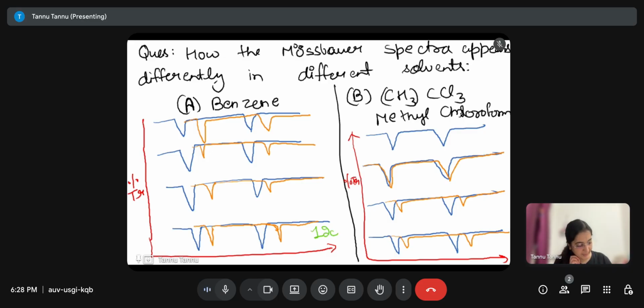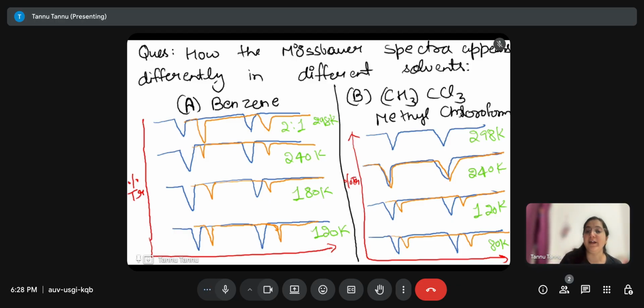So this is at 120 Kelvin, 180 Kelvin, 240 Kelvin, and this is 2 is to 1 on 298 Kelvin. Similarly, this is at 80 Kelvin, this is at 120 Kelvin, 240 Kelvin, and 298 Kelvin. So the spectral difference in the two solvents is, in benzene we see localized Fe2+ Fe3+ Mossbauer peaks at all the temperatures. But in case of methyl chloroform, at higher temperature, the Fe2+ Fe3+ peaks get delocalized. That is, the peaks get delocalized and they merge into each other.